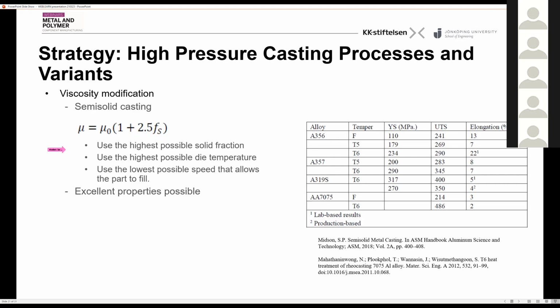In order to enable fill, you can also use the highest possible die temperature, because it aids the filling. And you can then reduce the fill speed. Even though you use a high pressure die casting system, you can significantly reduce the fill speed in semi-solid casting. And that means that you can reach a defect-free material.